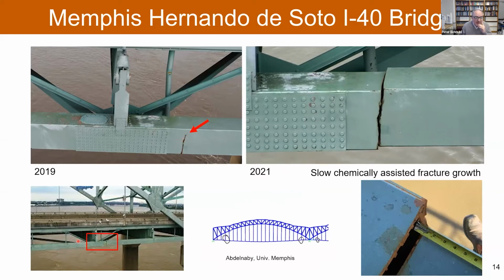Luckily, this beam is not really load supporting. It's preventing the deck from flexing. So it's stiffening the deck. But it's under tension. That's why it's opening up. But the bridge doesn't necessarily collapse because of this. That's the good news. And they fixed it in the meantime. Interesting to see is it's obviously completely rusted out, which tells me, also from the fact that it took years for this fracture to propagate across, that it was not a sudden event.